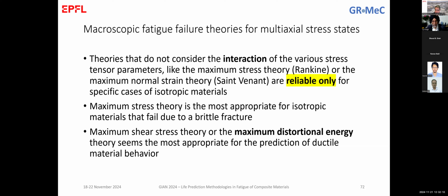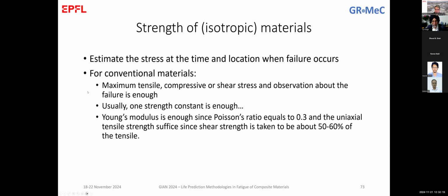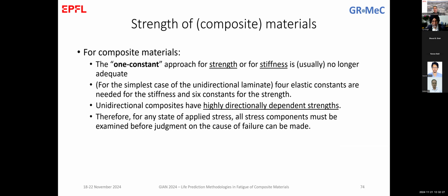Maximum stress and maximum shear are good models for isotropic materials, but are not good for composites. For composite materials, we usually need to assume a multi-axial failure criterion, taking into account all three components of the applied stresses in the calculations. And this is mainly due to the anisotropy of the material, especially when we have highly anisotropic materials. Imagine a carbon unidirectional fabric that has very strong properties in the direction of the fibers, but the properties transversely to the fibers are very, very low, which means that even with a very, very low stress in this direction, you might have failure of the material itself.